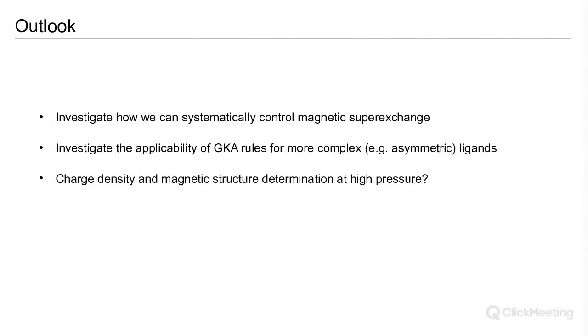Some of these frameworks are inherently prone to disorder, particularly when you have a molecular unit at the A site, which could have a lower point symmetry perhaps than the point symmetry of the framework at that site. So you can have positional disorder at play there and things like this. So some of these systems, they don't order well. As it happens, the dimethylammonium copper formate does order very well and does form beautiful crystals. And that's one of the reasons, of course, that the charge density studies work particularly well.